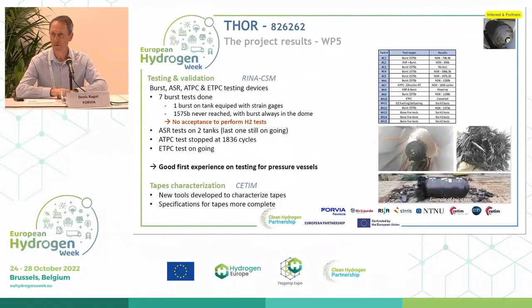Okay, so once we have the tanks, we have to test them. So 15 tanks were built, as I said, and we have made some burst tests. The first one was naturally to qualify for the EC79 or R134. So 7 burst tests. We have reached at the maximum 1475 bars, which is close to the threshold, 1575, but not enough to be able to go further with hydrogen tests. It was a pity for us, but with the delay we've got regarding COVID, we haven't been able to make an iteration step with the lessons learned we have got with this project.